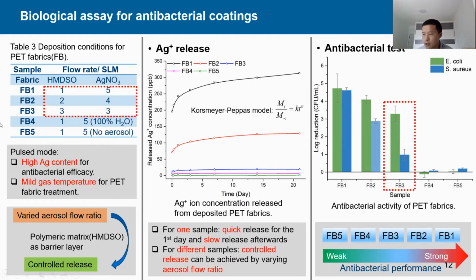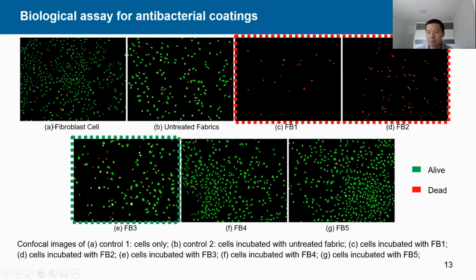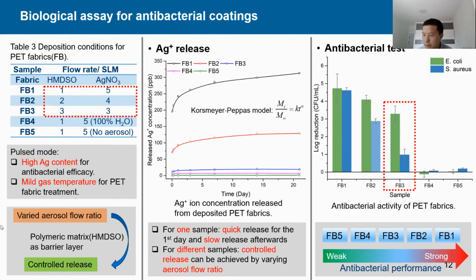And antibacterial effects of coatings were also examined by E. coli and S. aureus. Both bacteria were incubated with different fabric samples. After 2 days, the colony forming units were counted and their log reduction was calculated. Fabrics FB1, FB2, as we see here, show strong antibacterial properties, which are related to more released silver ions, while FB3 shows a moderate antibacterial efficiency.